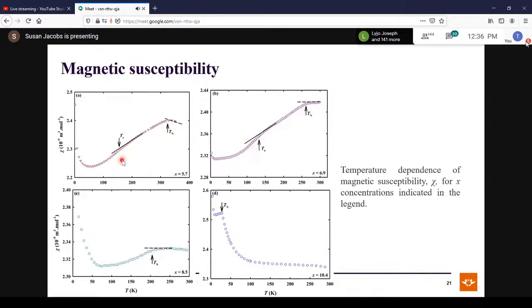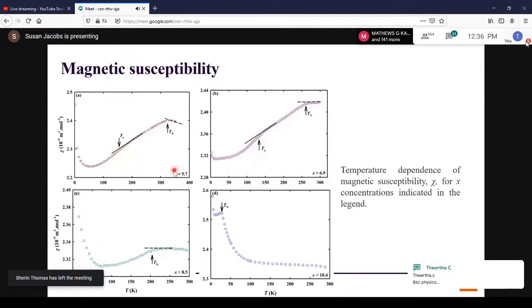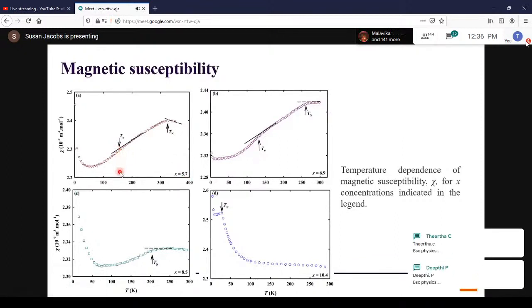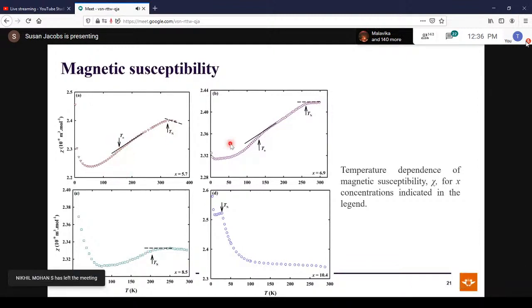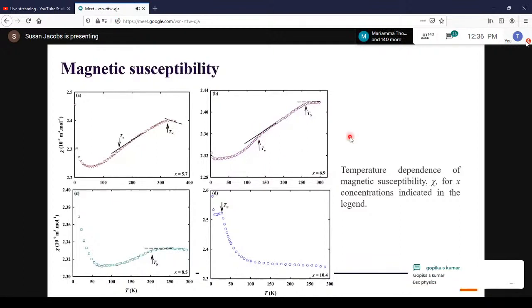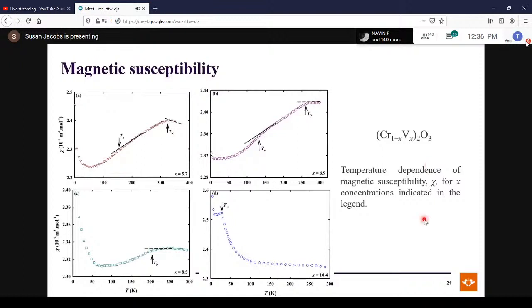Now, if you look here, the temperature for 5.7 atomic percent vanadium is close to, let's say, 150. Whereas for the 6.9 atomic percent vanadium, we see that the temperature is suppressed. It's below 150. So we suggested that this means that it's not just Cr2O3, but rather a vanadium-doped oxide of chromium.